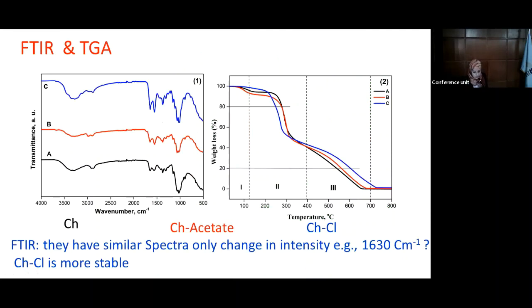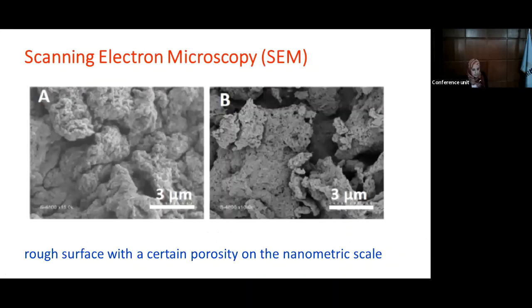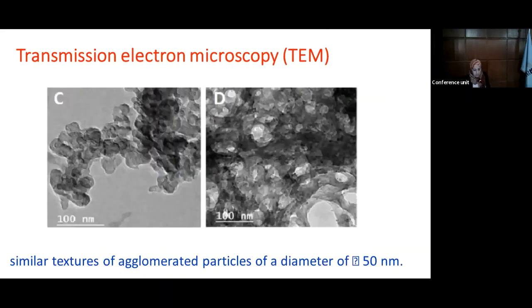We checked the structure of our product by FTIR. In chitosan we already saw the characteristic bands of chitosan, and for our derivatives we see a change only in the intensity of the carbonyl group, an increase of the intensity, meaning that it has attached the guanidinium group. For thermogravimetric analysis, we see our derivatives are more stable than the chitosan itself. We checked the surface of the products by scanning electron microscope, and we found that the surface is rough with some kind of porosity, and with the transmission electron microscope, we see agglomerated particles of diameters roughly 50 nanometers.